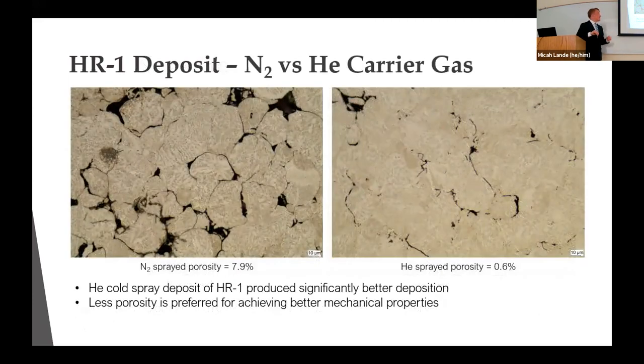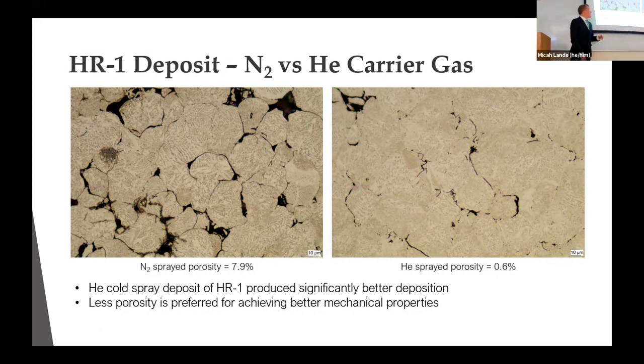And the same thing can be seen here on an optical microscope level, where on the left we have our nitrogen sprayed, and you can pretty clearly make out just about everywhere any kind of boundary in between the different particles, and it also has significantly higher porosity. For the helium sprayed, this is much more compacted together because the particles are able to fly at such a high velocity thanks to that boost from the helium gas. And again, our porosity here is significantly lower. So all that gives us an interesting reasoning for the changes in mechanical properties in a little bit.